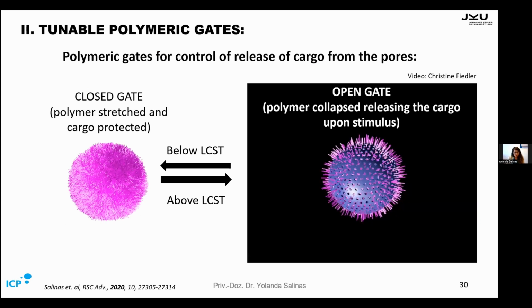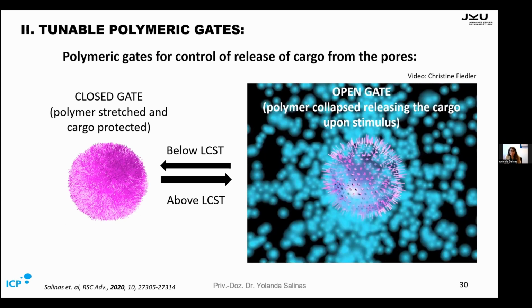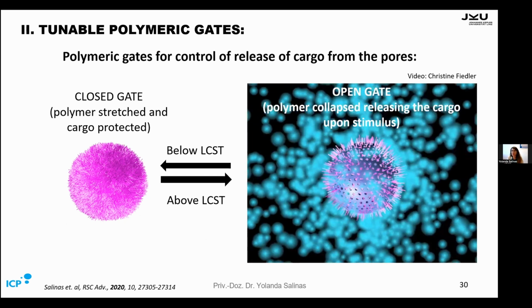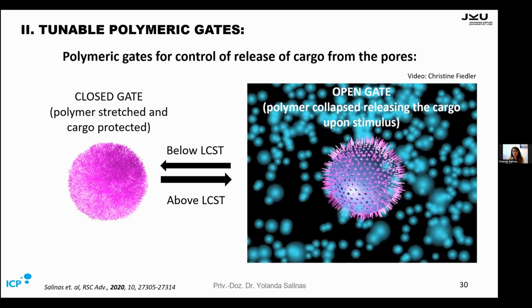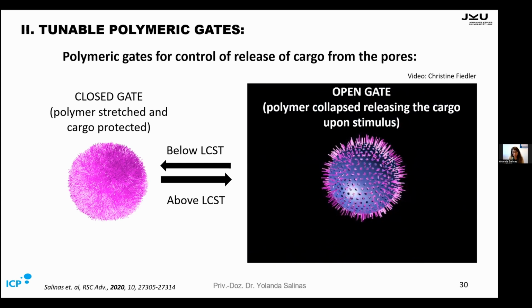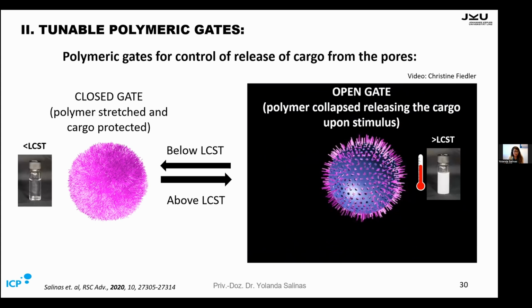So here we can see how these polymeric gates were used for controlling the release of the cargo. Once they are covering the particle, these kind of hairs are not allowing the cargo to be released. When the polymer is collapsed, we can observe that the release happens upon this stimulus. In this case, we created a polymer that was thermoresponsive. We can see here that the polymer in water was transparent and all dissolved. But when the temperature increased, we can see the aggregation of this polymer, forming a cloudy solution observable by naked eye.